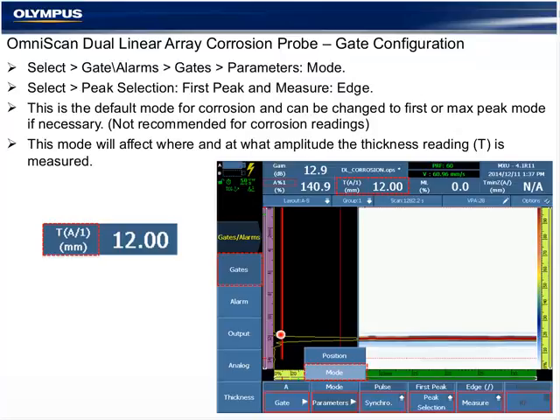So because we're not using auto gain correction, the amplitude of that signal in gate position will have a slight effect on the thickness accuracy. Using the normal defaults under very typical conditions, 0.25 millimeter accuracy should be well within the range of the inspection without much optimization of the UT or gate position for the range of thickness listed for each file.